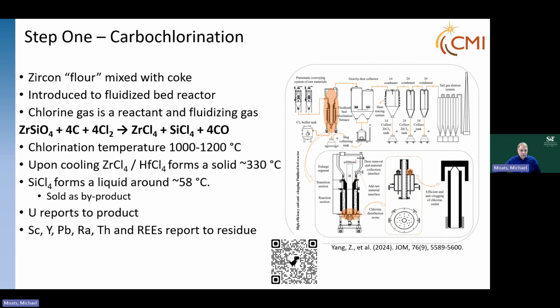They then go through condensers where the gas is cooled off. Zirconium tetrachloride and hafnium tetrachloride form a solid around 330 C, so they'll form a solid and we'll capture those. The gas will continue to be cooled. Silicon tetrachloride forms a liquid around 58 degrees C. That is sold as a product and is used in various chemical processing. It's a high pure form of silicon tetrachloride.